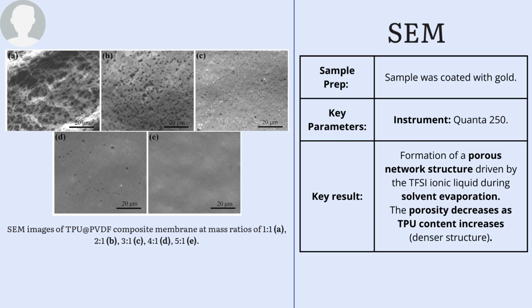In image A, at a ratio of 1:1, a highly porous sponge-like network is observed. The authors attribute this porosity to the presence of the TFSI ionic liquid during the solvent evaporation process. However, as the TPU content is increased, as seen in images B and C, this network becomes denser.